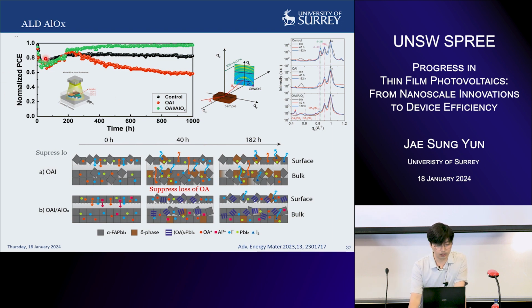So if you see the control sample, that's under continuous light illumination in nitrogen environment. You can see that the control sample has around 20% degradation. When you have this passivation layer, it slightly increases your efficiency. However, you can see that the stability got worse. The main reason is that this long chain cation just evaporates quickly under the light illumination, as well as the halide. So if you have aluminum oxide on top of this material, you can see, so that's the OAI sample and the OAI with AlOx sample.